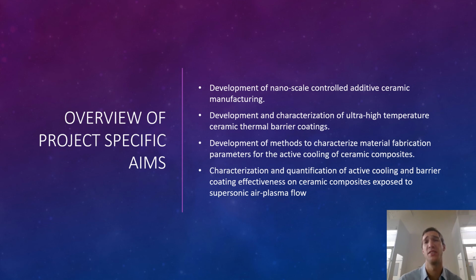Next up is also using this same novel robotic system to create the matrix in these CMCs, and using that to create ultra-high temperature ceramic thermal barrier coatings. And then we'll move on to characterizing material fabrication parameters so that we can reach a microscale controlled porosity, thus permeability, in these composites, which can be used for active cooling applications such as leading edges and hypersonics. The next step from there would be looking at and characterizing just how effective these newly fabricated CMCs and the respective active cooling aspects of these CMCs are when exposed to supersonic air plasma flows.